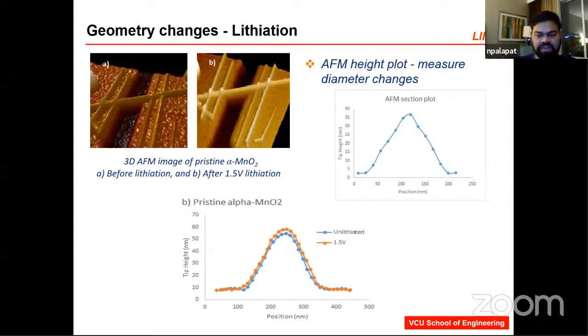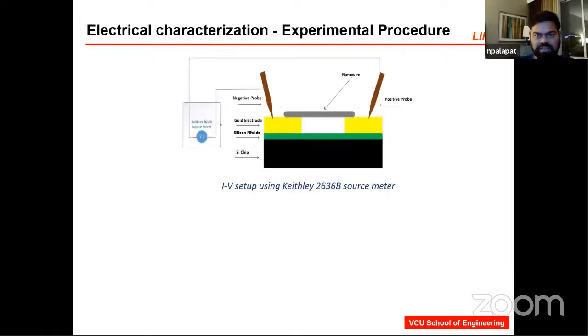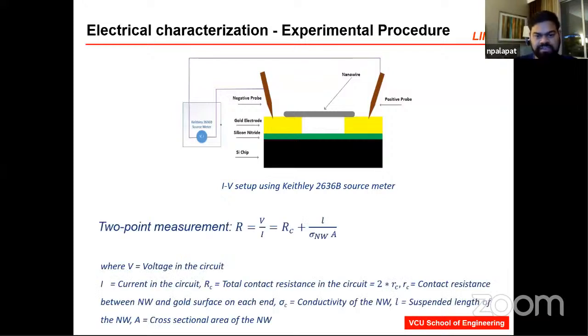Once the lithiation is complete, here I talk about the electrical characterization, how I was able to measure the voltage and current inside a single nanowire. If you recall the design that I showed, I have a large pad on the left and there are individual pads on the right. I connect probes to these pads and use a source meter, carefully using an optical microscope. I make a clear contact, and thereby I am able to measure the current and voltage using a two-point measurement technique. I have this equation, which is derived from the regular equation that we use to calculate the resistivity voltage in a particular circuit.